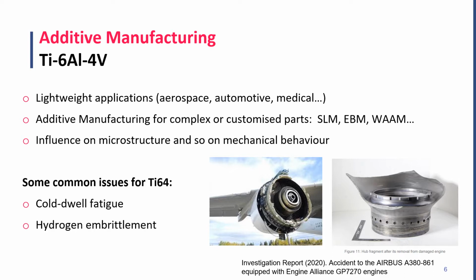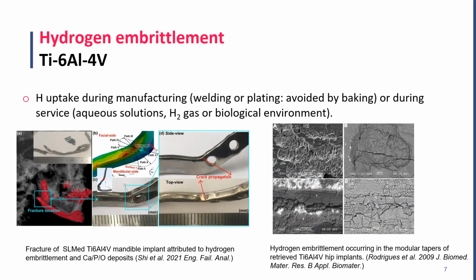Another common process is the failure of titanium alloys due to hydrogen, and this is usually known as hydrogen embrittlement. Some manufacturing processes, such as welding or electroplating, introduce hydrogen, and this can be outgassed in a baking post-processing, but of course this increases the production cost. Hydrogen uptake can also happen in service, especially in electrochemical reactions or when titanium is in contact with gaseous hydrogen.